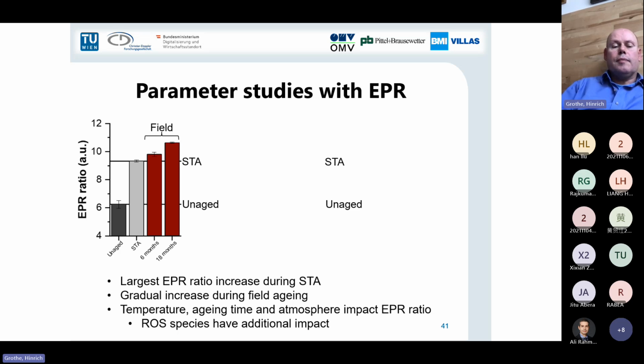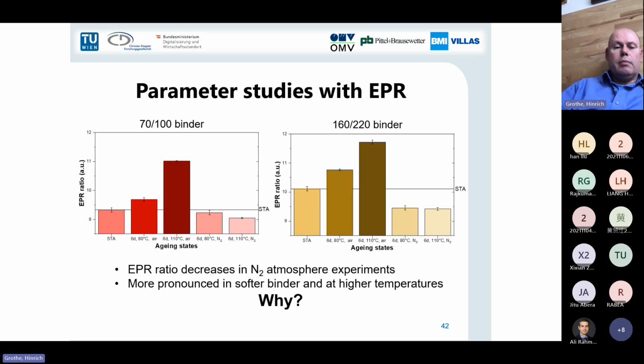And when you do so, you see the unaged sample on the left-hand side. You see short-term aging, and then you see temperature changes. You see then temperature changes under nitrogen in comparison to oxygen. And the moment when we apply oxygen species, so the ROS, we can really recognize that this EPR ratio is growing a lot. So the formation with OH radicals, with NOx, with ozone, is generating radicals in our material. That's an important message. And also there are differences, of course, depending on the binder. It's mainly the viscosity of the binder which is important. And also here it's a comparison between reactions just with nitrogen, which is inert, and then on the other hand, applying an oxygen-containing atmosphere where ROS formation is possible.